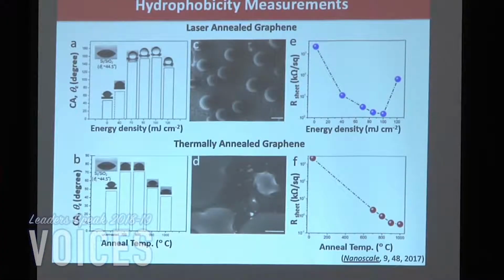That supplies an incredible amount of surface area, which is really important for catalysis, such as you need in electrochemical biosensing. But also, we can pattern that surface so that the graphene can turn into a surface that's non-wettable or super hydrophobic. So when we first print it, it's generally hydrophilic. Surface water contact angle would be around 45 degrees. When we treat it correctly with the laser, we can get that close to 155 or 160 degrees. So it's a super hydrophobic surface. So now that you have a non-wettable surface, that could be used for a lot of things. Maybe this is a surface you would put on an airplane wing to help it de-ice or prevent ice buildup. Or maybe it's put into a biosensor where you don't want biofouling to occur or other things to collect on that surface, and it'll stay clean. So that's a neat material property that we can get just by patterning that surface.